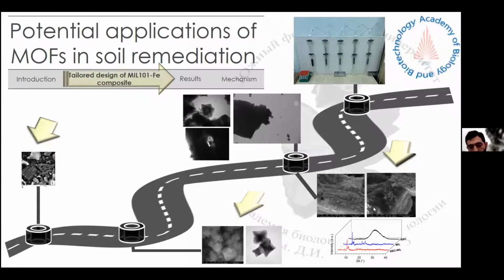Here you can see a photo of the material that we synthesized successfully, and here is the XRD of our material. We use a rice husk biochar since it offers very good cation exchange on its surface, and it can be a very promising material for taking up heavy metals. Then this is the structure of MIL, and this is the structure of the composite. The XRD pattern shows the same peaks, so adding the biochar inside the composite didn't destroy the structure of MIL. Also, I calculated that the crystallinity has decreased, so it means the particle size has been reduced. MIL size is slightly smaller.